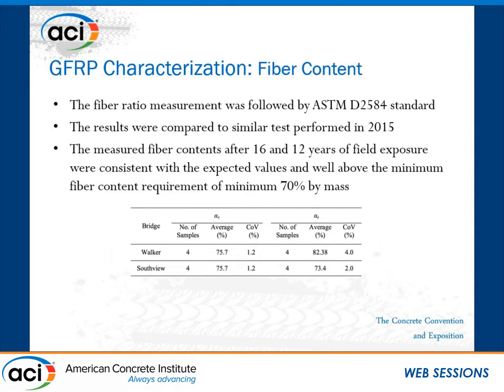And finally, the fiber content. The fiber content was performed following the ASTM D2584, and the results again were compared with the test produced in 2015. The measured fiber content, as you can imagine, was exactly in the expected range and still well beyond the minimum requirement of 70% by mass. So the results were 82 and 73%, which are in the exact range that we expect to see for the fiber content ratio.